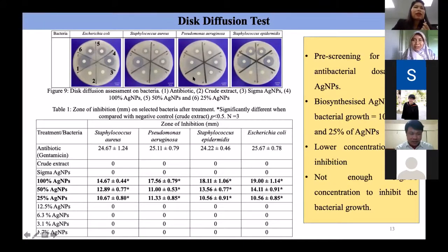So from the diffusion method, we can see a very big zone of inhibition. From the study, we can conclude that the concentration of the silver nanoparticle can be used from 25% up to 100%. And there was no inhibition for the lower concentrations. It is most probably because there was not enough silver nanoparticle at those concentrations.